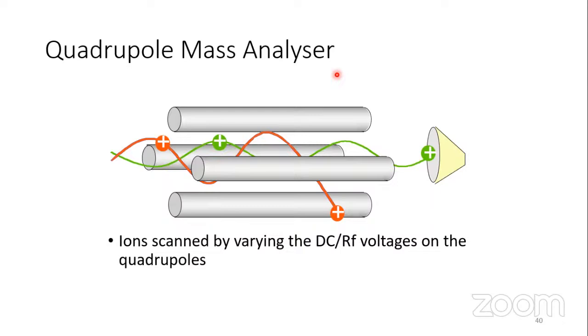In the quadrupole mass analyzer, as you can see, there are 4 poles. Each pole is about 20 to 30 centimeters in length and has a diameter of about 8 to 10 millimeters. These 4 poles are exactly of identical size. What we apply onto this quadrupole is a DC and RF field, that is, radio frequency and a DC voltage. Both are applied in such a way that at one moment, if these 2 opposite rods are positive, the other 2 rods will be negative and the charge varies. So if these 2 are positive at one moment, the very next moment these 2 will become negative, and at that time the others will be positive.